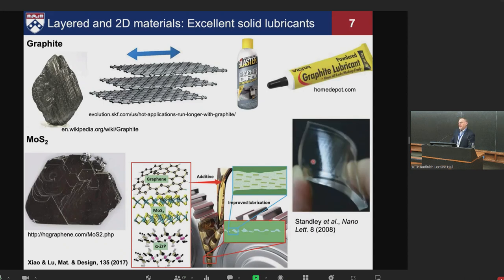And one of the reasons why I think there's a lot of excitement about these is because in addition to having low friction and low adhesion, you can control the friction and adhesion. It's hard to get high friction to be low, but if you're starting with low friction, you can often do things to bring it up. And so if you think about flexible electronics, there are many opportunities to take advantage of the amazing electronic and thermal and optical properties of 2D materials while also taking advantage of how flexible they are. But to assemble and manufacture these, you often need to adhere or de-adhere or transfer different layers. As you bend it, you may get small amounts of sliding and shear stress between the layers. So the tribology is important for the electronic applications that integrate these materials.